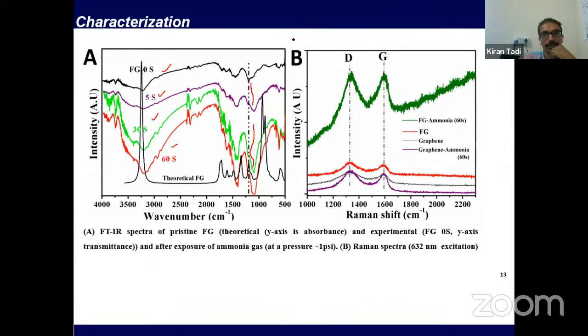We also took the ID Raman spectra. In this Raman spectra, we didn't see any difference in the ID by IG ratio before and after the exposure of ammonia, so we can say it is just electrostatically interacting, but no bond formation is taking place, because if the ammonia were attaching to the graphene, the ID ratio would definitely get affected.